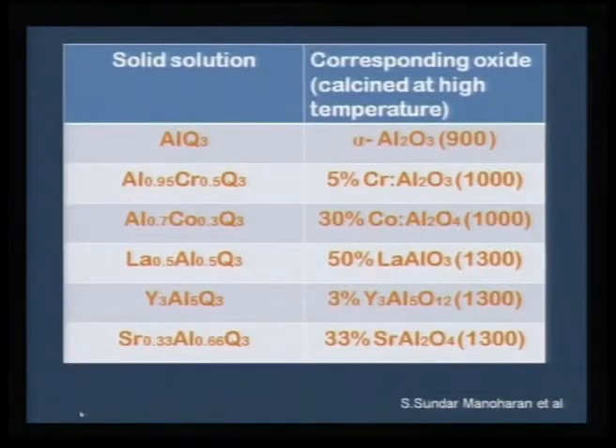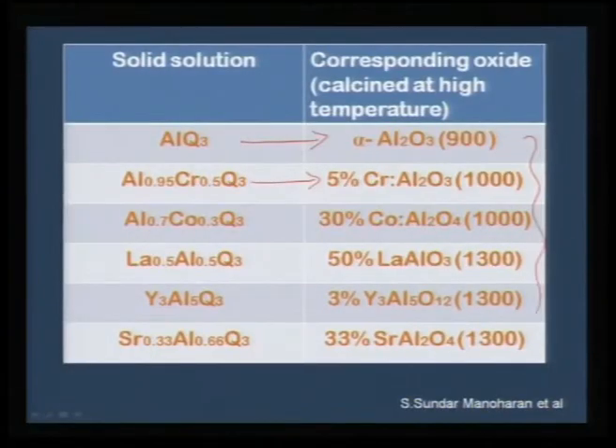So, what do we do with this? If I am going to now anneal these compounds, what I am expecting is the corresponding metal oxide, and if it is a solid solution, I should not see a mixture of oxides, but only one particular phase of oxide. So, the corresponding oxides that I am anticipating here, with different heat treatment, either 900 or 1000 or 1300, which we can vary, because these are all the ranges where these oxides are reported to form. So, I can just try to heat it to see whether I am getting a single phase compound.